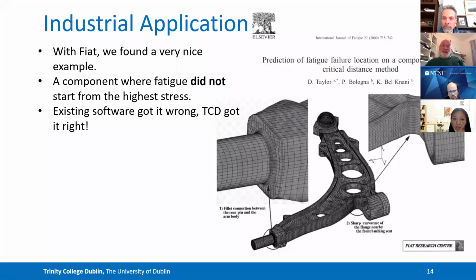The exciting thing about this one was that when they did the finite element model, there were two areas of high stress. There was this point here, and there was this point here. And this point on the left has actually the highest hotspot stress. So the maximum stress in the whole thing is here, but it wasn't failing from that. When they did fatigue tests simulating real use, it actually failed over here, from another point where the stresses were pretty high, but not as high as here.